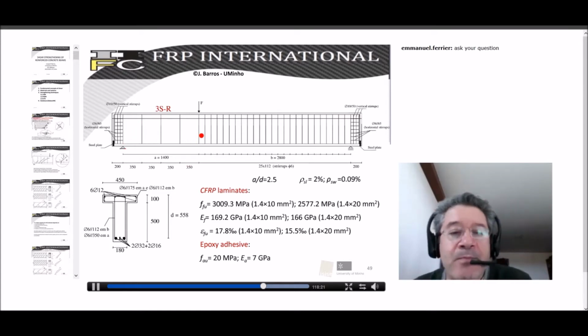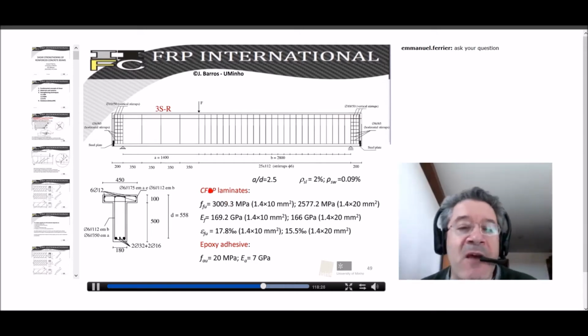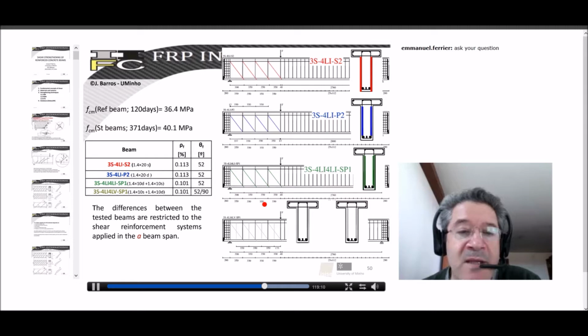So we used CFRP, carbon fiber polymer laminates, with an ultimate strength of about 3000. So laminates of 1.4 by 10 cross section, but we also used laminates of 1.4 by 20. And in this case, for these laminates, the tensile strength is a little bit lower, so it's 2577 megapascal. The Young's modulus is 169 and 166 gigapascal, and this is the ultimate strain. And we used epoxy adhesive with a tensile strength of about 20 megapascal and a Young's modulus of 7 gigapascal. And look what happened.